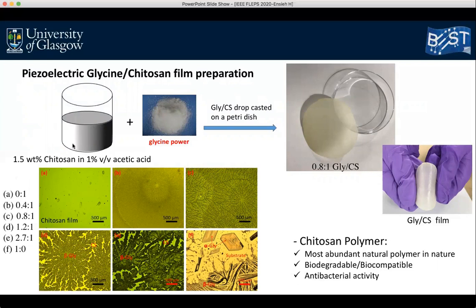So first we prepared a 1.5 weight percentage chitosan solution by mixing chitosan powder with the acetic acid solution, and then a series of glycine chitosan solutions were prepared by dissolving different amounts of glycine powder in the prepared chitosan solution. And then a film of glycine chitosan was prepared just by simple solution casting technique and drying at room temperature. Here figure A shows optical image of plain chitosan, and figure B, C, and D show 3 morphologies of spherulite in the film cast from glycine to chitosan with different ratios.